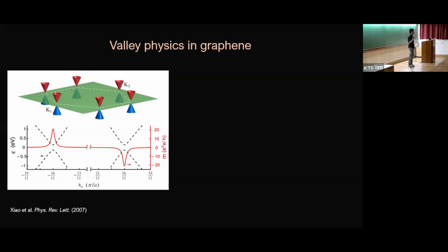Now, one of the ways to detect the Berry curvature is that you apply an in-plane electric field in the system, and the charge carriers in K and K prime valleys will move to the opposite Hall probes, and you measure Hall resistance, which is the valley Hall effect. Now this is of course interesting, but if you take 2 graphene layers and rotate one with respect to another by a magic angle of 1.1 degree or so, the system becomes much more tunable.